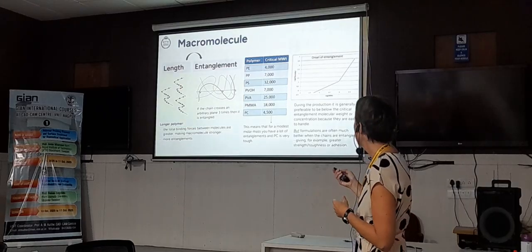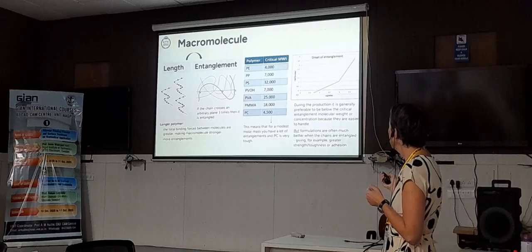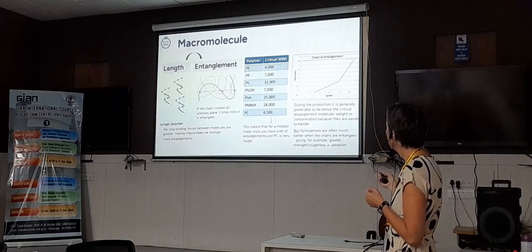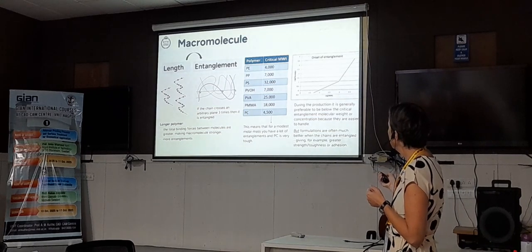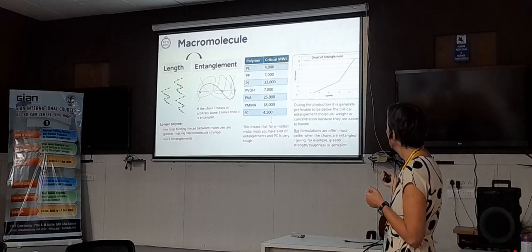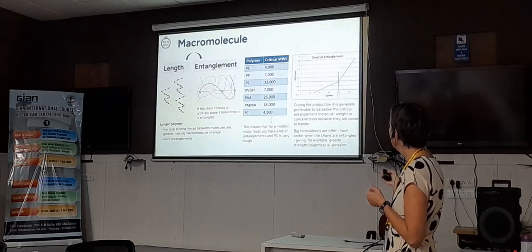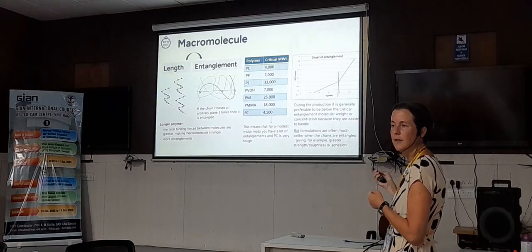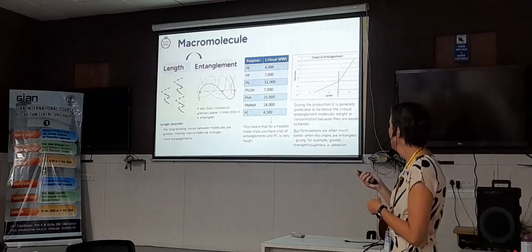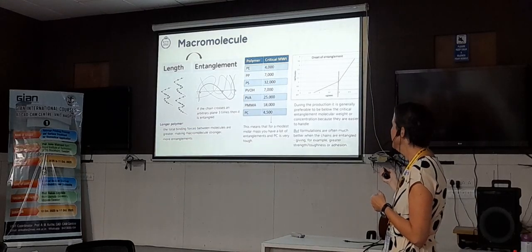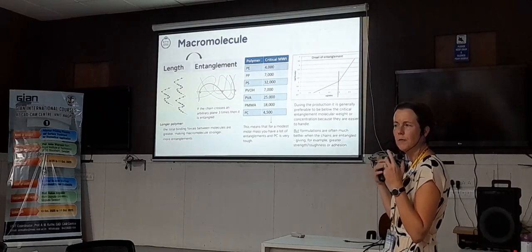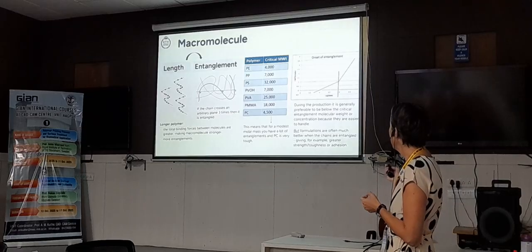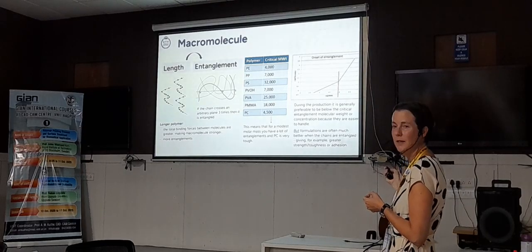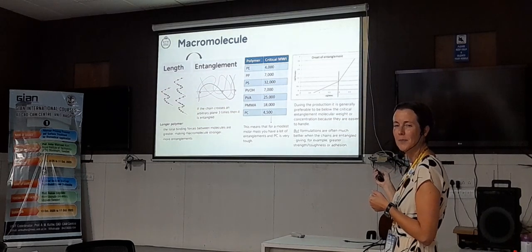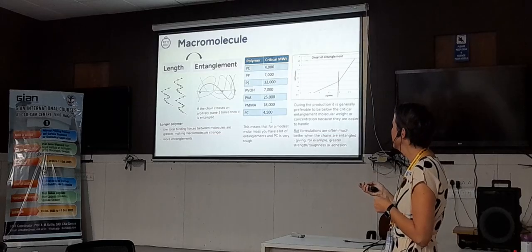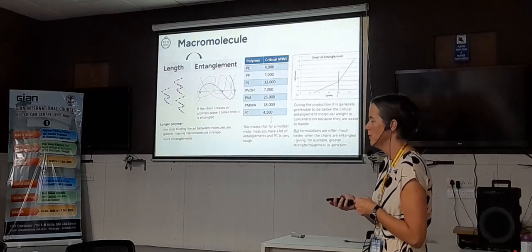And this is why it's so important. And this is also a bit tricky part when you then do the printing, because this is the viscosity on the y-axis, and they have the molar mass on the x-axis. And then you can see that the viscosity is quite low at lower molar masses, but at one point it increases drastically, and that's where it starts to entangle. So for printing, it might be easier to be here. The molar mass is lower, so you get a lower viscosity and it flows better. But for the end use and the mechanical properties of the product, you want to be here, because then you get better mechanical properties. So that you need to have in mind, and it's dependent just on the length of the macromolecule.